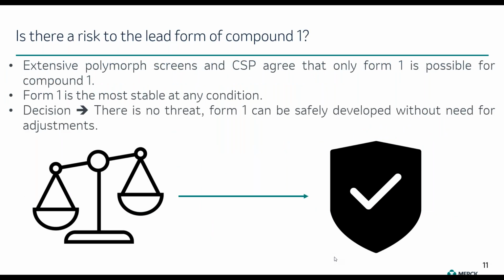So how did we digest this information? Is there a risk to the lead form of compound 1? Both extensive polymorph screens and CSP data agree that only form 1 is possible for this compound. Form 1 is the most stable by quite a large margin at any condition, both in lattice energy and in free energy at room temperature. So we decided that there is no threat to form 1 and that it can be safely developed without the need for adjustments or some extra screening work in this case.